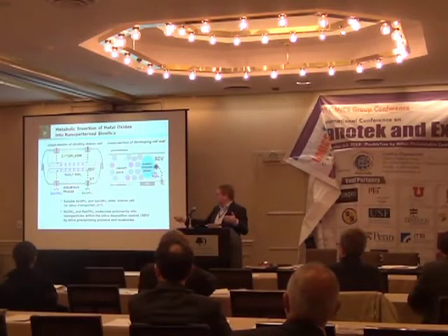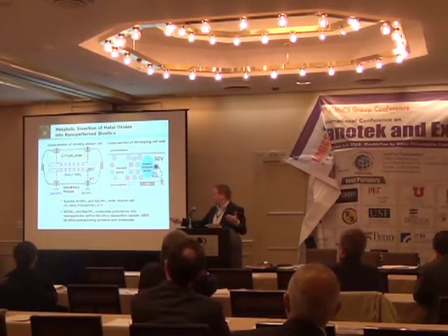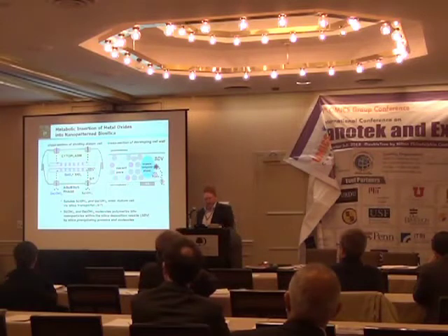It has a silica transporter built into the cell membrane, which pumps in the soluble silicon, or in our case, we also feed it a foreign substrate, soluble germanium. This material is then polymerized into nanoparticles based on an organic template phase within this deposition vesicle. And this allows you to impart foreign metal oxide nanophases embedded within the silica matrix.